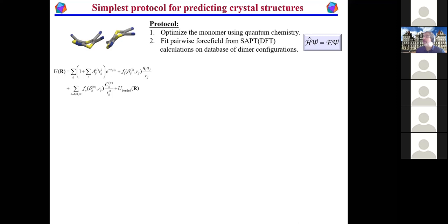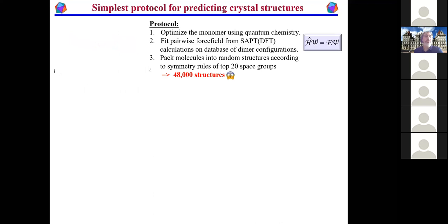It's not going to be perfect because this kind of fitting is done in the gas phase and you want this to work in bulk phases. But at the end of the day, that's what you're going to get. Then you take your force field and you start packing molecules into random structures, let's say, according to the symmetry rules of some subset of the 230 space groups, maybe the top 20 that appear in any of your databases, all right? That's going to give you something like 48,000 structures, which is way, way too many, okay?